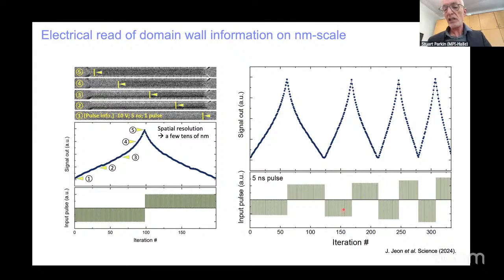And as we increase the intensity of these current pulses, the number of pulses needed to move the domain wall from the left to the right or right to left shrinks. And in this way, we could demonstrate that we could resolve the position of a domain wall to a few tens of nanometers and follow it continuously as it moves from one end to the other.